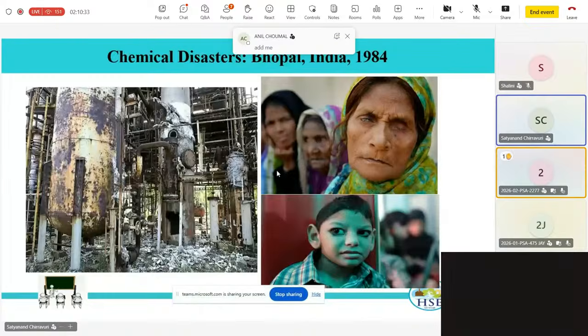And so methyl isocyanate, which is a low boiling liquid, boils at around 40 degrees centigrade, which is similar to the boiling point of methylene dichloride. This, in fact, came out because there were multiple failures. There was a refrigeration failure wherein you are supposed to contain methyl isocyanate itself, the temperature rise not to happen, so you are supposed to have a refrigeration system in place.